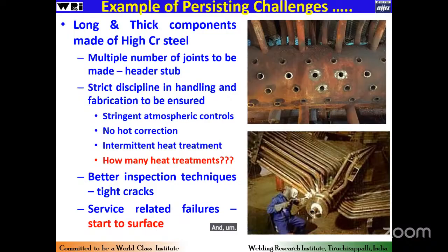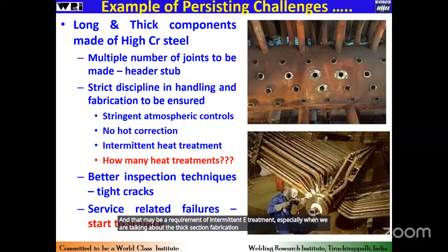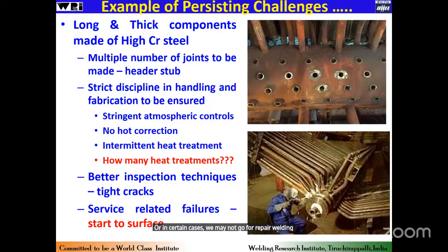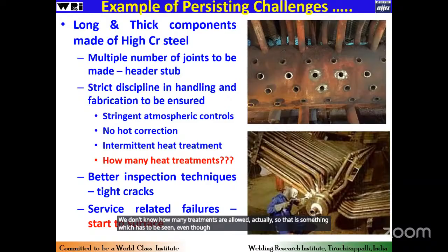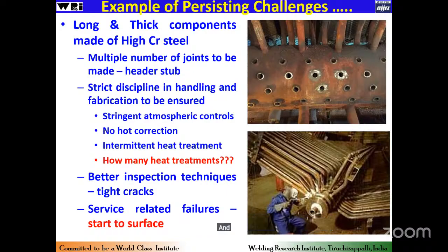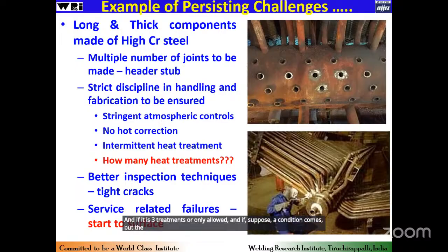And there may be a requirement of intermittent heat treatment, especially when we are talking about thick section fabrication. We may not be able to complete it in one go, or in certain cases we may have to go for repair welding after intermittent or interstage examination. So when we talk about the intermittent heat treatments, we don't know how many heat treatments are actually allowed. So that is something which has to be seen. Even though as a thumb rule we say 3 heat treatments, we don't know what is actually tolerable. And if only 3 treatments are allowed, and a condition comes up during fabrication, then it has to be manipulated in such a way that we are able to complete the entire fabrication with 3 treatments. So that is something which we have to really address.